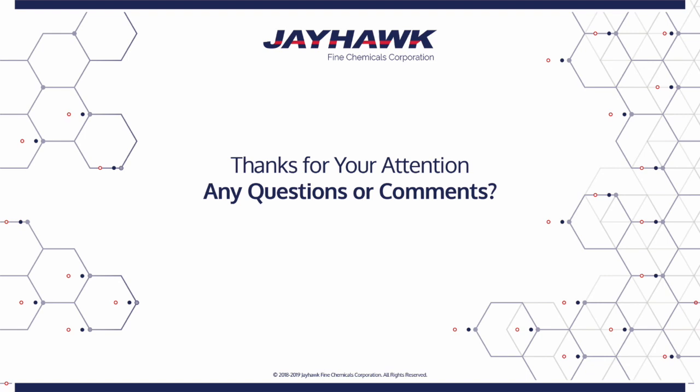Anyone with comments? Yeah, this is Boris. I'm in agreement with that, and that's pretty much what we wanted to demonstrate today, especially with the inclusion of these different accelerators to show how you can achieve that balance. There's a lot of give and take here, as you can see, and it depends what you're looking for. If you're looking for a high Tg development, you have to steer towards certain accelerators, or actually, in some cases, no accelerators. If you're looking for faster cure or lower temperature cure, you've got to swing back and start looking at those different families of accelerators in terms of what you need for your process. Maybe even your own processing conditions are the dominant factor. What your current process can do with regards to how high can you dial the temperature, how slow can you run your line. Those may be the limitations too.